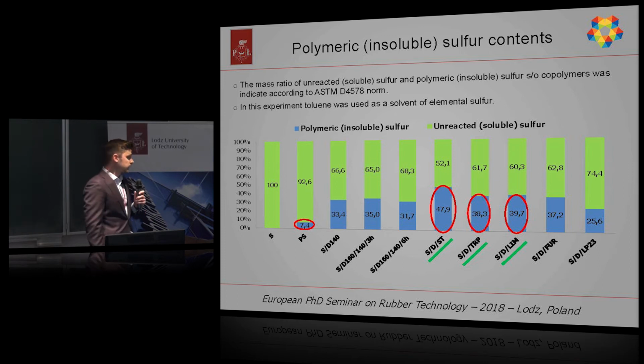And looking at the results, the highest polymeric sulfur contents exhibit copolymer with styrene, then with limonene and turpentine. And the average sulfur content in all copolymers is approximately 30 to 35%. And when it comes to the polymeric sulfur, as I said, is unstable, so the contents of macromolecules are very low, and more than 90% are unreacted sulfur in form of orthorhombic. So polymeric sulfur may behave during vulcanization process as classic orthorhombic sulfur.